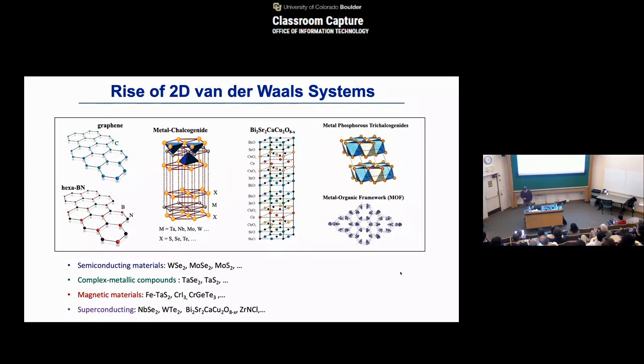So there is a variety of these 2D materials available, but on top of that, because of the van der Waals interactions between the layers, unlike molecular beam epitaxy growth, where interface consideration for chemical compatibility as well as mechanical compatibility is important, here you don't have to pay that much attention, simply because of the weak van der Waals interaction, which allows us to build, in principle, three-dimensional structures out of these layered materials, and quickly come up with quasi-three-dimensional van der Waals heterostructures out of combinations of different materials.